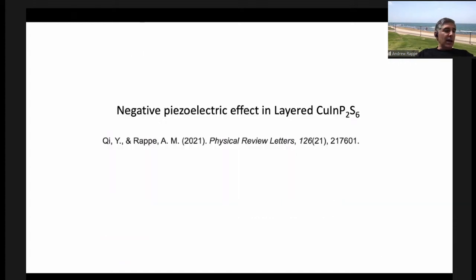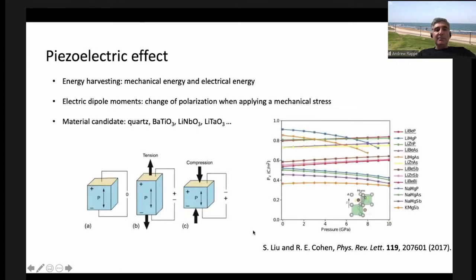Okay, so now I will tell you about one or two other areas where pressure and stress can influence the bonding in materials. And so one of these is analyzing the negative piezoelectric effect in layered copper indium phosphide sulfide. And this work was just published about a month ago.